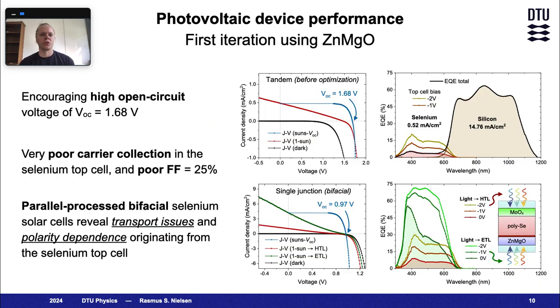The first results showed an encouraging open circuit voltage of almost 1.7 volts, but the carrier collection in the top cell is terrible, and the fill factor is also very low. And to better understand the consequences of these modifications that we needed to introduce in the transfer of our process to silicon, we fabricated bifacial single-junction selenium top cells in parallel with the tandems.